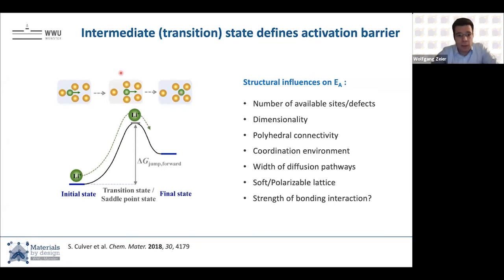We need a high number of available sites. I mean, if there's a lithium already sitting here, the lithium can't jump there. We need a certain dimensionality. We ideally need 3-dimensional conductors over 1-dimensional conductors, because real materials have defects and we can have blocking effects. Usually in terms of structures, we discuss certain polyhedral connectivities, where face-sharing polyhedra are better. And there's a question of how much your coordination environment changes. Here in this case, from a 3-fold to a 4-fold coordination, is this beneficial for the ion or not? All of this influences the energy landscape.